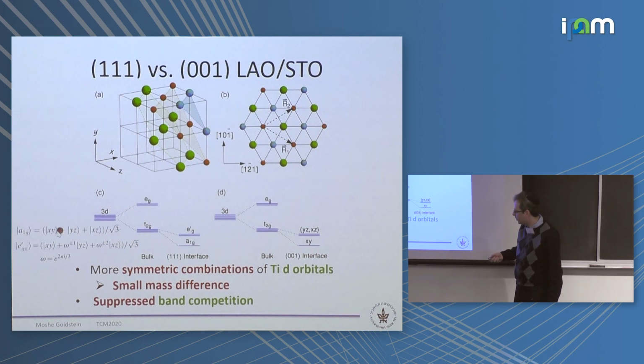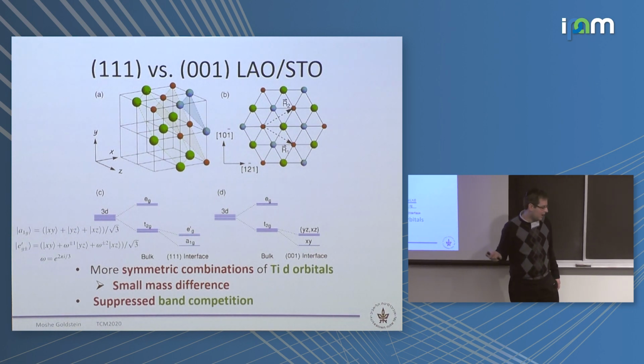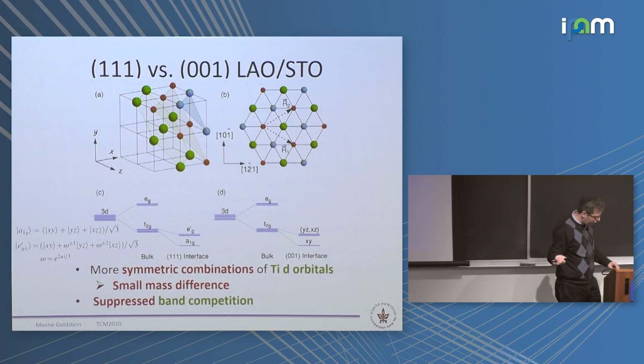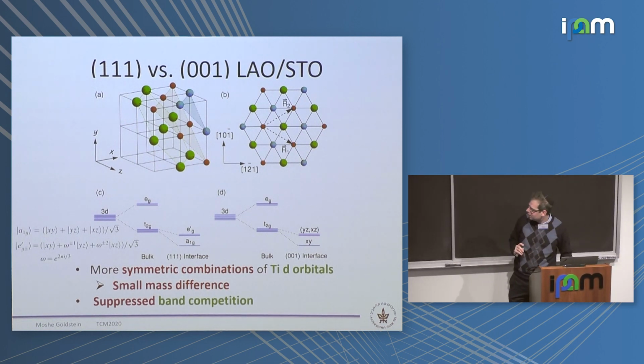And those are much more symmetric combinations of the orbitals. In particular, the order between them is not determined by the confinement. They basically have almost the same mass. The order between them is some secondary effects, which we took from DFT, and because the masses are quite the same, this non-monotonicity of density of one of the bands should not happen here. So if we perform a measurement, we should expect to see different things.